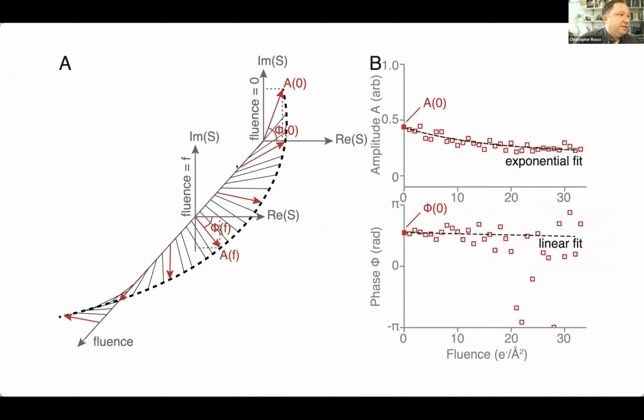So one way to think about this is if you're fond of phasors, or thinking in sort of real and imaginary parts of complex numbers, what we're trying to do here is determine the trajectory of this complex number as a function of fluence. And we actually map that back to 0. And you can do this using imaginary and real, or amplitudes and phases, however you like. But in the end, you try and go back here to 0 with as accurate a fit as possible. So we're working on what's the best way to do this right now. The basic idea is that we can actually rewind this movie back to the point where there is absolutely no damage to the thing you're interested in looking at.